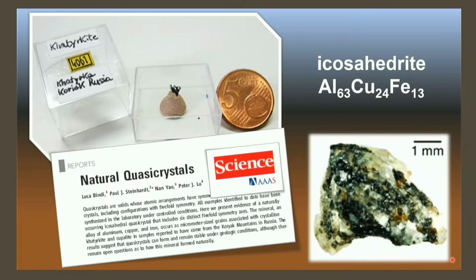And when we realized that we have a new chemical composition, a ternary alloy of aluminum, copper, iron, and a new crystal structure, we decided to propose this mineral to the International Mineralogical Association with the name icosahedrite, to reflect the internal symmetry. We got it approved, and so this aluminum 63, copper 24, iron 13 is the first naturally occurring quasicrystal.